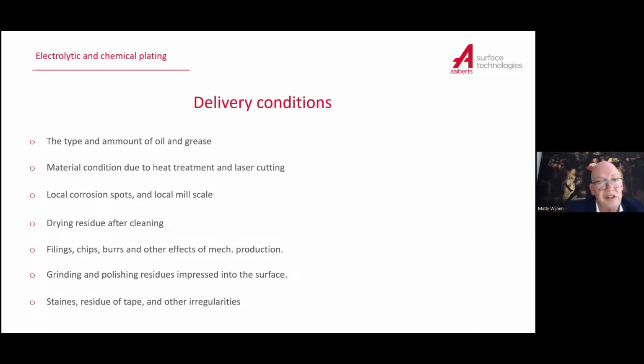Local corrosion spots: we have to etch the corrosion away, but you also etch your parts where the corrosion spots are not there, so we attack your material.